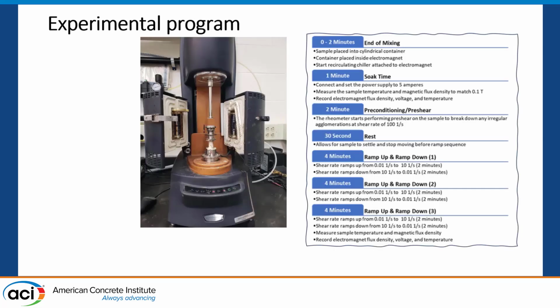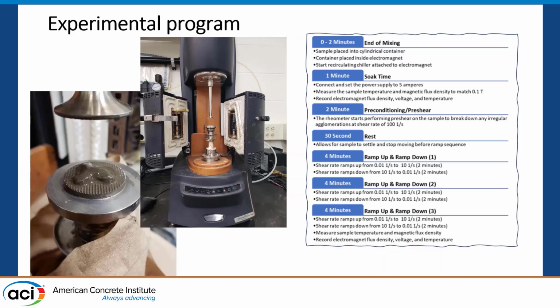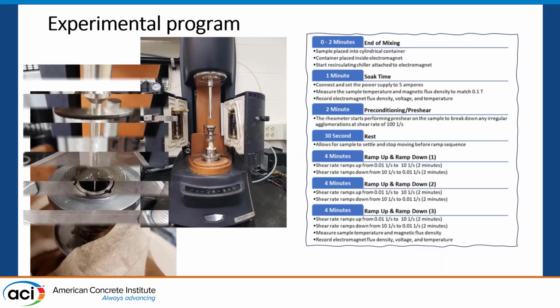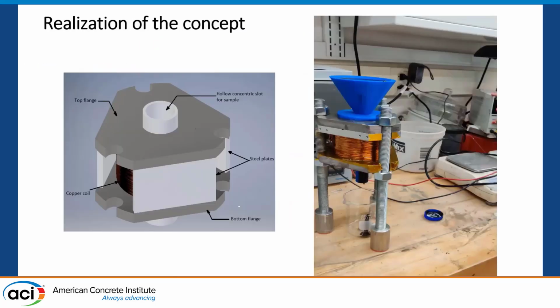And again, this is our setup, a classical rheometer, which we used for different experiments. And we tried different geometries, parallel plates, stirred plates, and they didn't really work for the range of viscosities and the range of shearing stresses which we tested. So we had to switch to vane geometry. And in addition, to control the magnetic field, we had to build an electrical magnet, and we use a constant field, but it can be easily switched to AC as well. And you can see one of the first experiments which we ran quite some time ago.